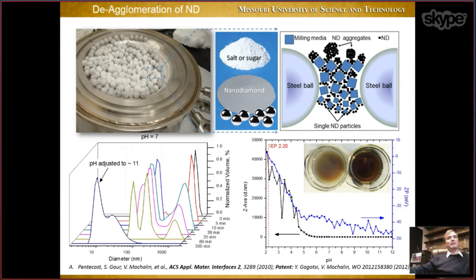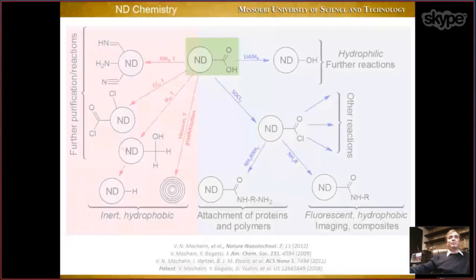And actually nobody in the nanodiamond community still knows why pure, well-dispersed nanodiamond has this dark color, because diamond is transparent, right? So you would expect the suspension to be clear. But it turns out no, and the better you disperse it, the darker is the color. So it's one of these puzzles in the nanodiamond community which still waits to be resolved.